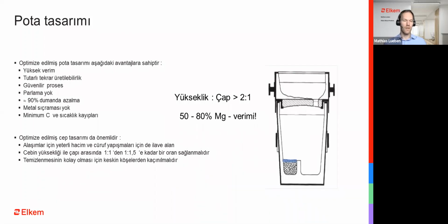Some aspects on ladle and pocket design. An optimized ladle design achieves the following advantages. You will get a high recovery, as you can see, with a proper height to diameter ratio of 2:1. It is possible to achieve high magnesium recovery of about 80% with a consistent reproducibility. With this kind of ladle construction, there's no flare and about 90% fume reduction without any metal splashing. Minimum carbon and temperature losses are also achievable.